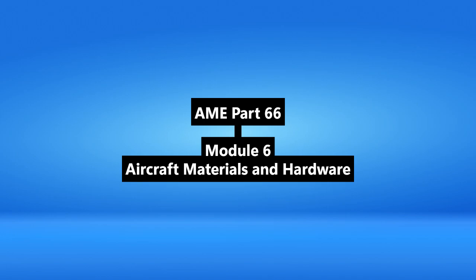Exactly. And interestingly, you can't directly Rockwell test really thin stuff like clad aluminum sheets accurately, because the indentation would go through the thin, hard cladding and be affected by the softer core underneath. You'd need micro-hardness testing for that. Interesting. Okay, that's a solid grounding in ferrous metals.